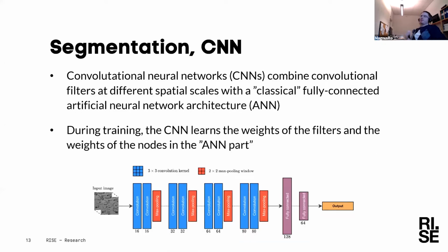But then, as you may suspect, this is not likely going to be the state of the art for this type of problem. We looked into convolutional neural networks as well, and I'm not going to talk about that because I realize the audience knows all this stuff. But basically, what we used as an input for the CNN was roughly the same data that we used as input for the random forest, but we didn't pre-process it. So we took essentially the same 3D box and plugged it into a 2D multi-channel CNN, and we investigated different sizes of this box to find the optimal size. And eventually we used this classical CNN structure with convolution layers, max pool layers, and finishing off with some fully connected layers to once again make the same classification into pore and solid, or pore and non-pore.